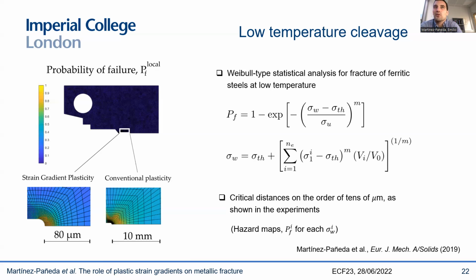But this doesn't really tell us much, right? Because in a way, we are calibrating the data. It just tells us that there's a big difference with conventional plasticity. However, what made a difference was the fact that we calculated these probability of failure maps, and we saw that if you had conventional plasticity, then your probability of failure, your hazard maps, were distributed over tens of millimeters, while if you have gradient plasticity, then your probability of failure was restricted to tens of microns. And we know from the experiments that the critical distance in these materials is typically tens of microns. So it seems that we're going in the right direction.